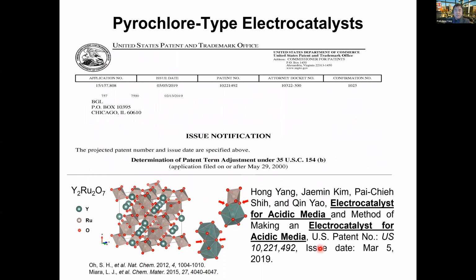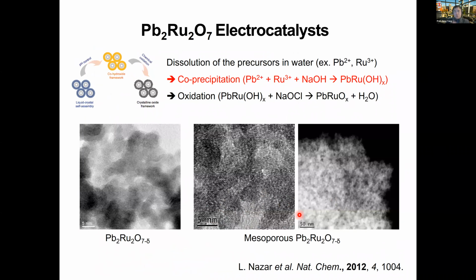So we chose this particular system, and more importantly, we started looking into acid-based media. In the remaining time, most of the OER catalysts I discuss will be in acidic media. Okay. One of the challenges, of course, is stability. In the early days, this is from Linda Nazar's group, also focused on battery development, and also interested in making the pyrochlore type of solid and using it as an electrocatalyst. They tried to use a mesoporous structure to do it, and there is a challenge in making that into a mesoporous structure while keeping it very stable.